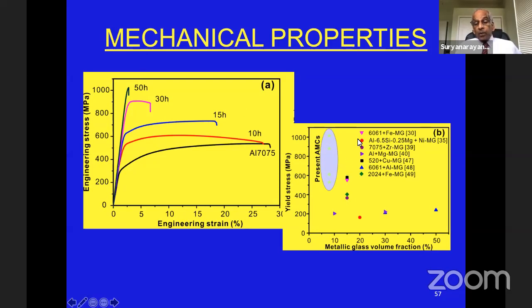And now, if you look at the comparison of the present aluminum matrix composites with the other types of composites, and if you plot yield stress versus metallic glass volume fraction, you're able to get a very high yield strength, even at a low volume fraction. Obviously, if you increase the volume fraction, this is going to be somewhere here even. And therefore, we have achieved the goal of increasing the strength.